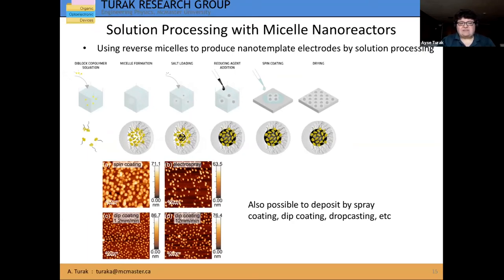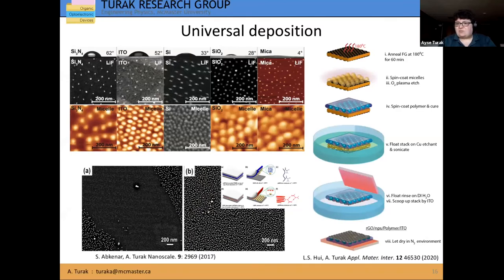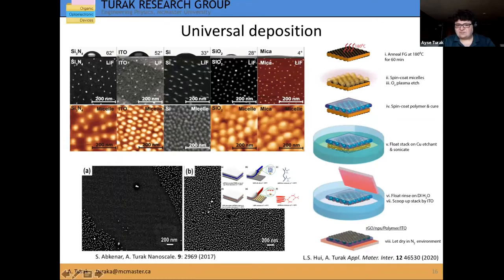Not only is the ability to deposit in different methods universal, but it's also possible to deposit on different surfaces in a universal way. The type and amount of particles that come out are all kind of agnostic to the surface energy, which makes it really exciting for producing on different surfaces that are generally hard to template or decorate with nanoparticles. We've even developed in our lab some ways of approaching temperature-sensitive or plasma-sensitive materials using different transfer printing approaches, including elastomeric stamps and graphene as a mechanical support for the nanoparticles, which also allowed us to have a nanoparticle-graphene composite put into devices to improve efficiency.